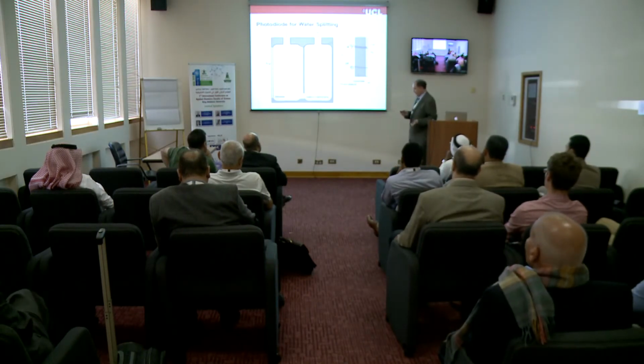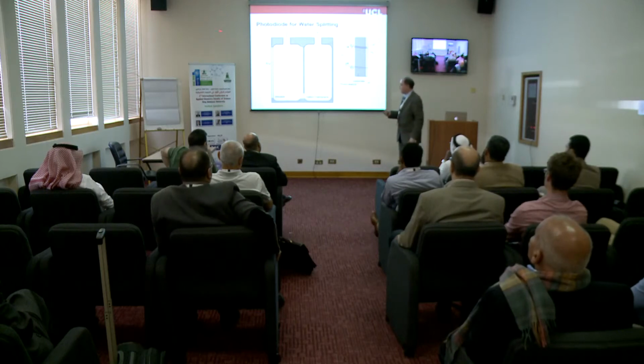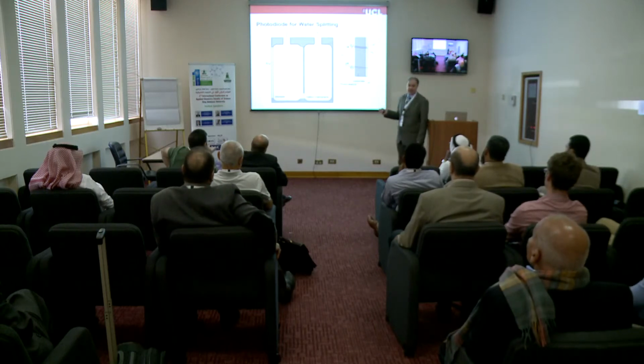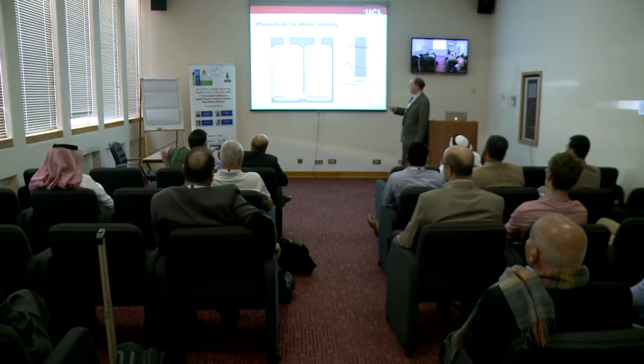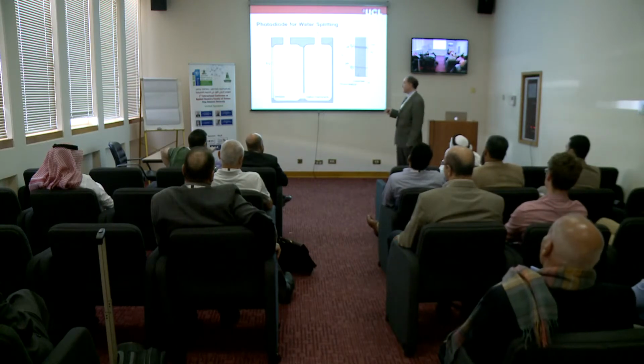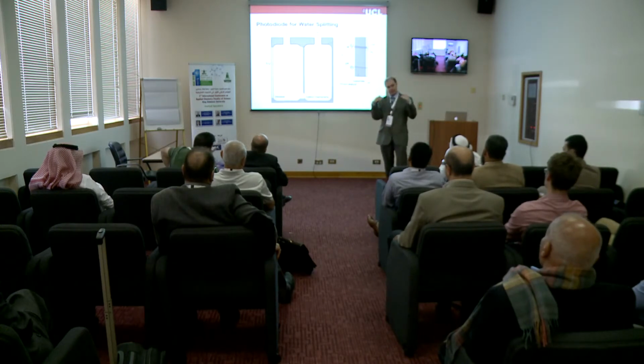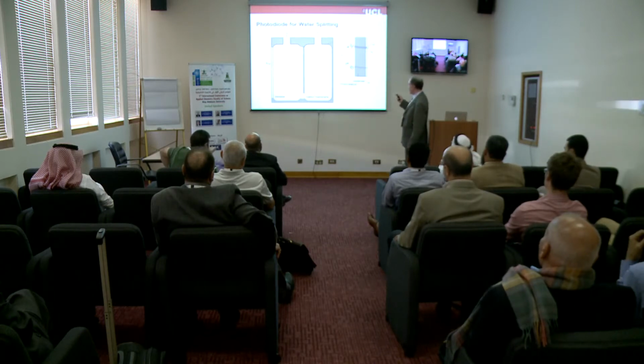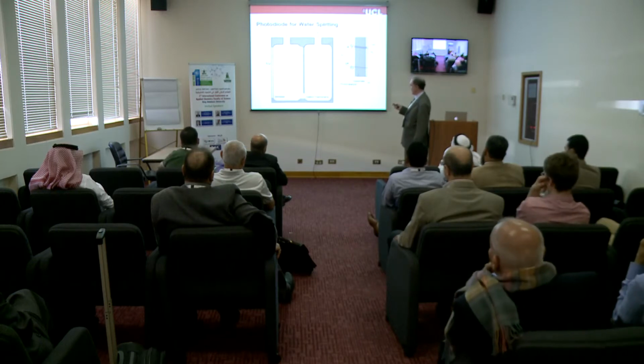Now, one other area that I just wanted to mention while we're talking of videos is we're also looking at water splitting. And the idea here is that you use sunlight on a photocatalyst surface to split the water into oxygen and hydrogen. We had a paper related to this membrane which was published in Nature Materials 2 years ago and has had nearly 300 citations so far. So we've worked out what is the optimum ratio for anatase and rutile forms of titanium dioxide to make the world's best photocatalyst. And we've then incorporated these materials into the photoanode.